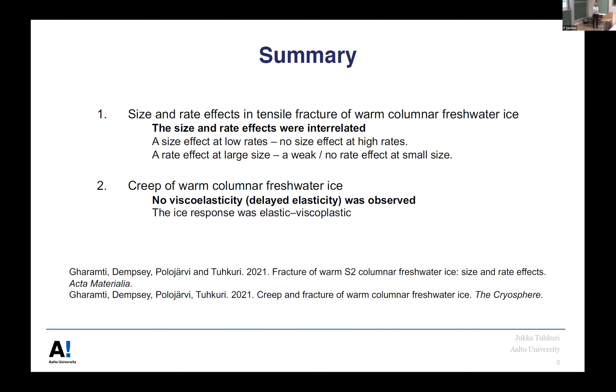Please remember our main results. Size and rate effects are interrelated. We have known for decades that size effects and rate effects exist independently, but now we observe that they are interrelated. There is a size effect at low rates and no size effect at high rates. We observe the rate effect at large size, but no rate effect at small size — and that last point is critical, because so much lab work is done at small scale.